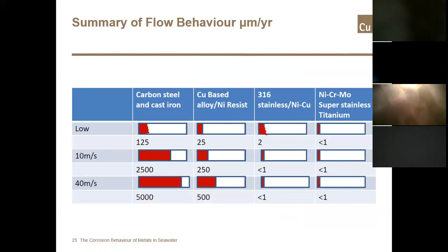So, we can actually recap on the flow behaviour of the materials and how they perform under different flow rates. And as you can see, the carbon steels and cast irons offer quite significant corrosion rates under even low flow rates. The copper-based alloys offer a significantly lower rate of corrosion under reasonable flow rates, but when you get down to the higher flow rates, then this can cause problems with them. The 316 and the stainless steels, the nickel coppers, their corrosion resistance systems rely on oxygen being fed to them, so they actually enjoy the higher flow rate. And the nickel, chromium, molybdenum, and the super stainlesses, titaniums, etc., again, don't have any real effect of increasing flow behaviour.